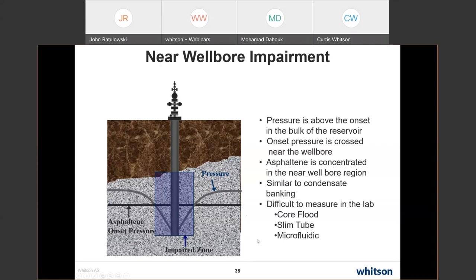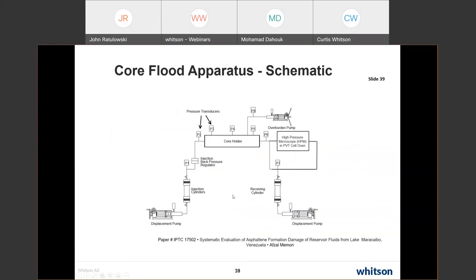So this is just showing the core flood apparatus. It's pretty common. What we would use is composite cores, which is a problem in itself, but that was all we had. And so you'd get these stacked cores, you'd measure pressure along the length of the core, and you would look over time at how the asphaltene built up and impacted the permeability. And the trick, again, like I said, was I have to be above the asphaltene onset when I go into the core, and somewhere in the core, I have to fall below that onset pressure.